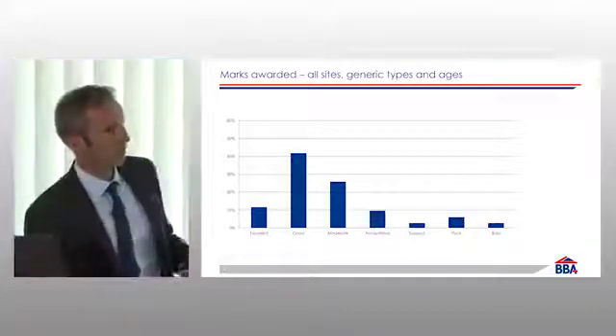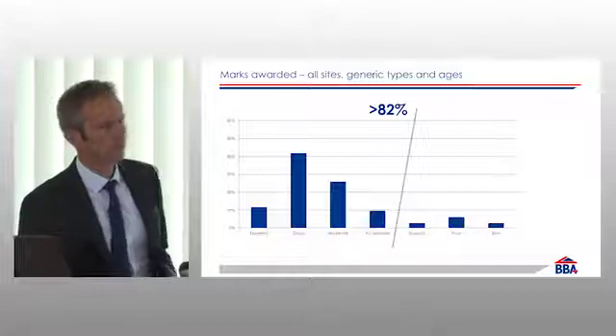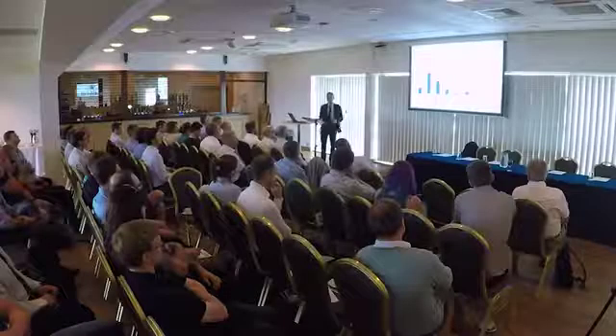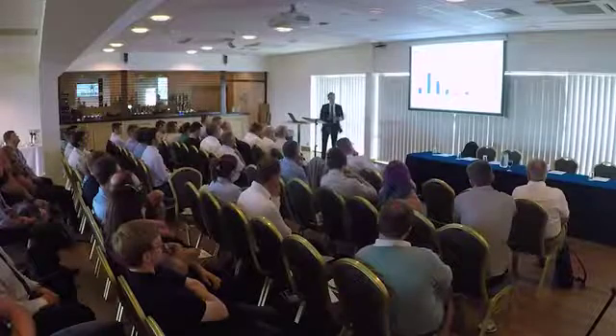Out of all of those inspections that we did in those sites, 82% were above acceptable. And I'm not going to tell any of you, if you've got experience of sites that were poor after like 2 years, that it's a very small percentage, because that is what's happening on your network and what's happening to you. But we went out and did a random selection, just went around the country, and this is what we found. So we did find poor sites, we did find bad sites, we did find suspect ones, but the majority that we saw were actually in reasonable condition.